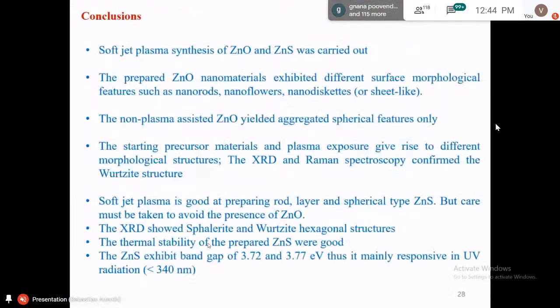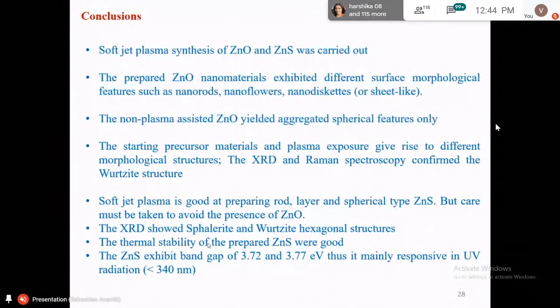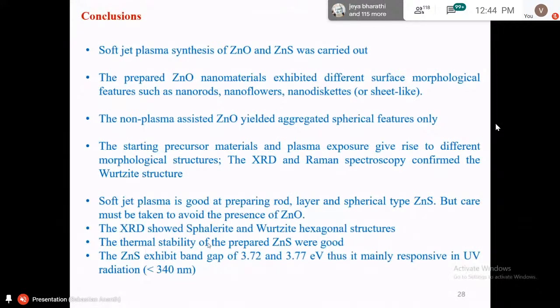So what happened so far in this research is that soft jet plasma was utilized to synthesize zinc oxide and zinc sulfide. The prepared zinc oxide nanomaterials exhibited different surface morphological features such as nanorods, nanoflowers, and nanosheets. The non-plasma-assisted zinc oxide yielded only aggregated spherical features. The starting precursor materials and plasma exposure give rise to different morphological structures. The XRD and Raman spectra confirmed the wurtzite structure. In the case of zinc sulfide, different structures were also found: one-dimensional, layer, and spherical structures were achieved.